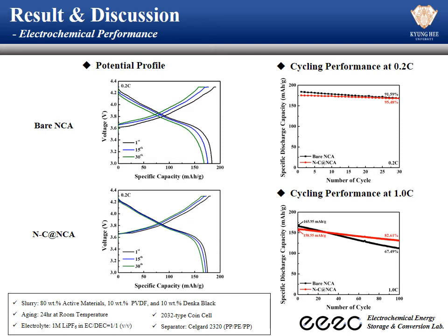Even in the case of 1C rate, which is a high rate of charge and discharge, NCA has a higher initial specific discharge capacity than N-C@NCA, but after 100 cycles, the retention is 67.49% in the case of bare NCA and 82.61% in the case of N-C@NCA. So nitrogen-doped carbon coated NCA is slightly inferior in terms of initial capacity because the formation of the coating layer can act as an impediment factor in intercalation and deintercalation of lithium ions, but in terms of the cyclic performance, it can be seen that it is improved because the coating layer acts as a barrier and improves the structural stability of NCA.